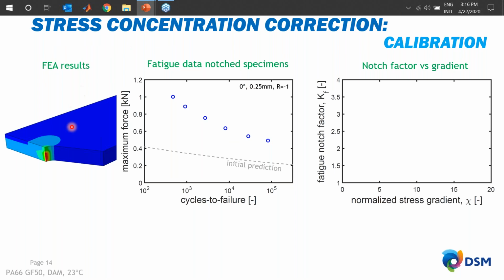Because as you might know, if you do a finite element calculation, so this is a calculation on the notch bar, this is 1/8 of the notch bar. So you have a symmetry axis here, a symmetry axis on this plane, and a symmetry axis here on the back. And if you do this on this double-edged notched bar, you will always find a huge stress concentration, or a huge stress amplification behind the notch.